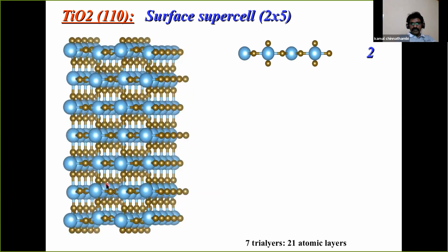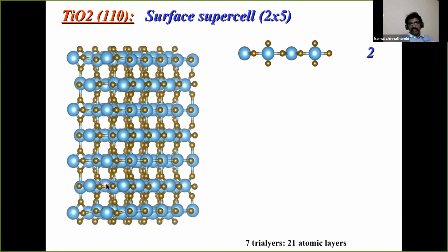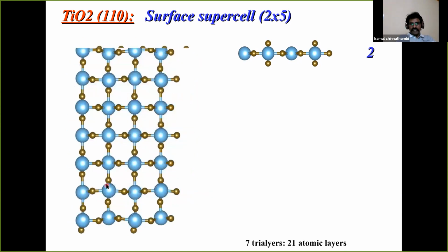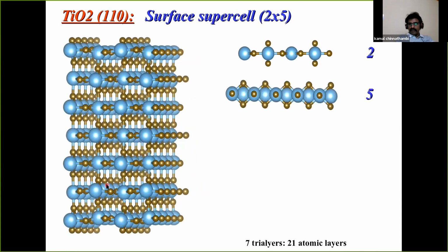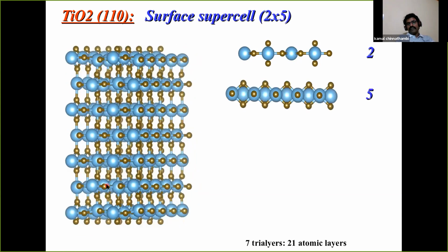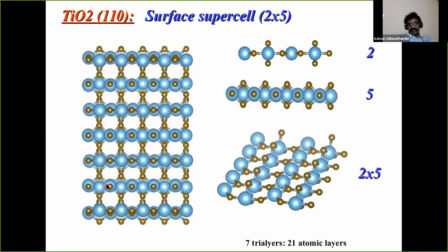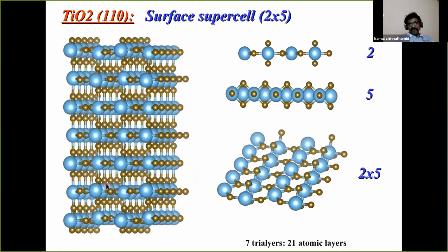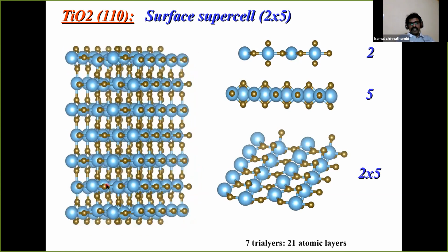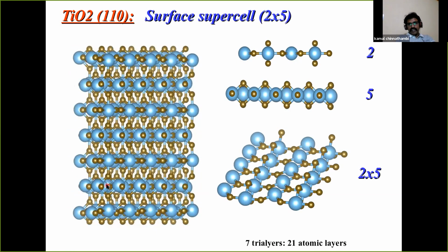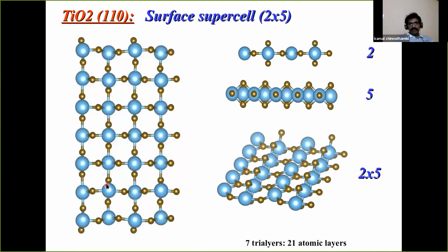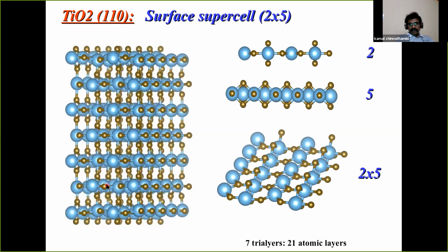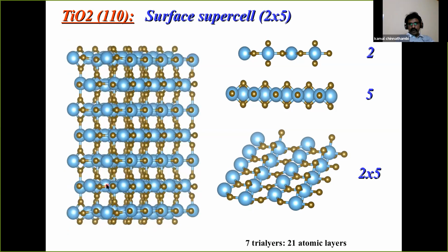In our case, I chose 2 by 5. In the A direction, we have 2 unit cells, you can see the 2 repetitions. In the B direction, we have 5 repetitions, which makes 2 by 5 as the surface. In the 2 by 5 surface supercell, we have 20 titanium atoms and the remaining 40 oxygen atoms.